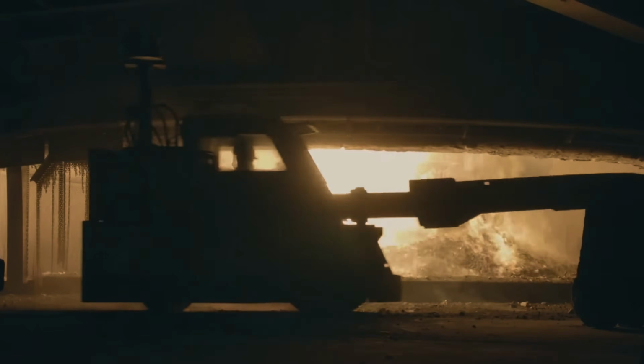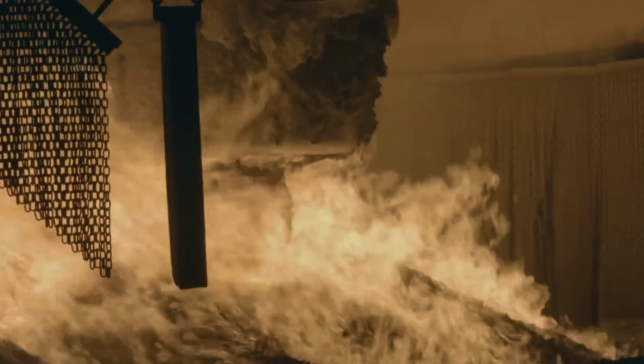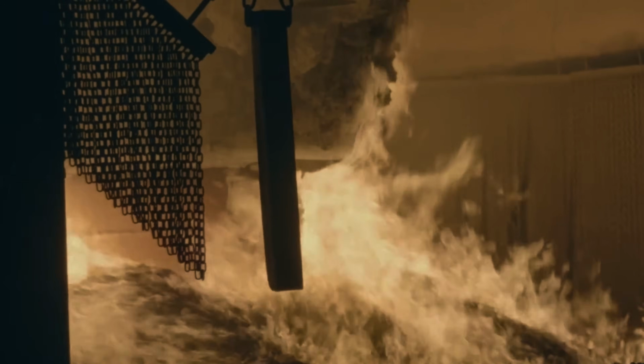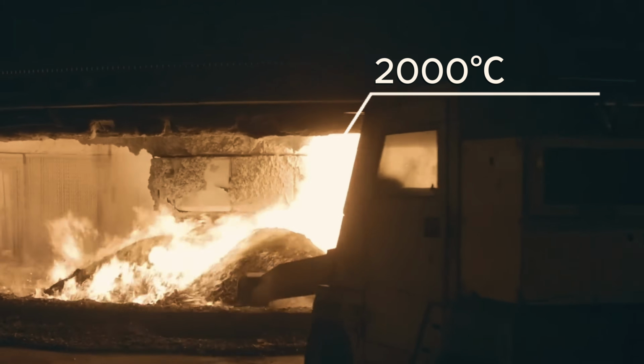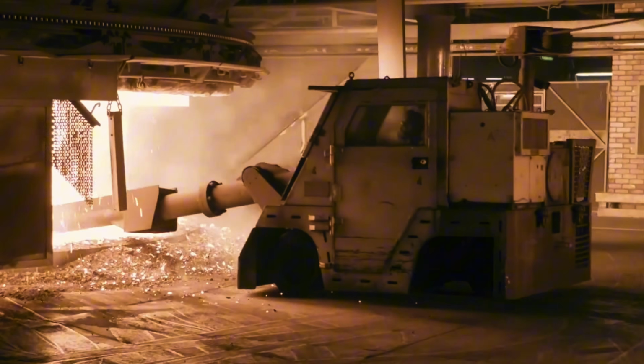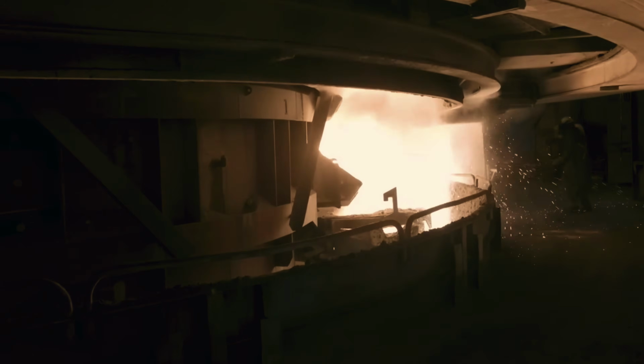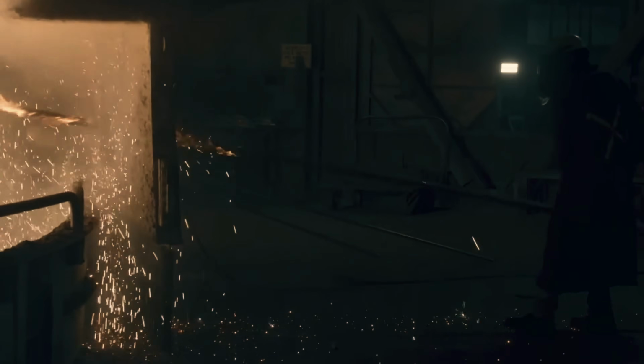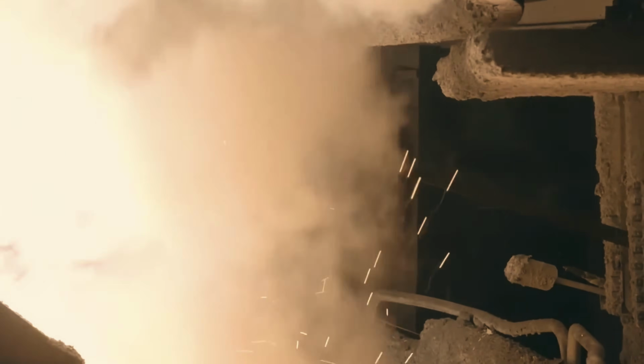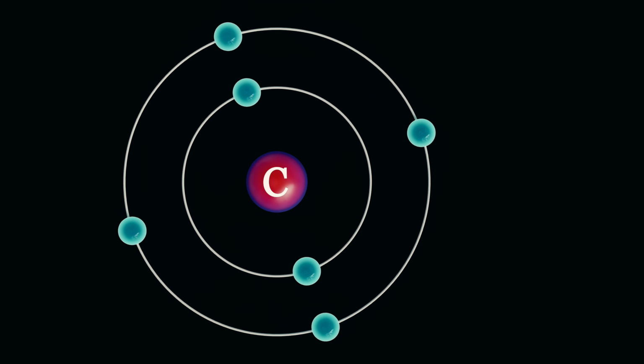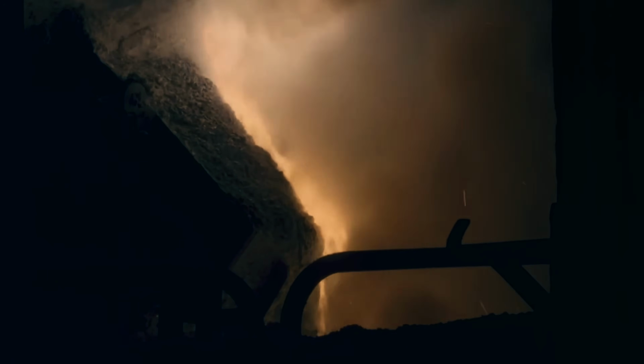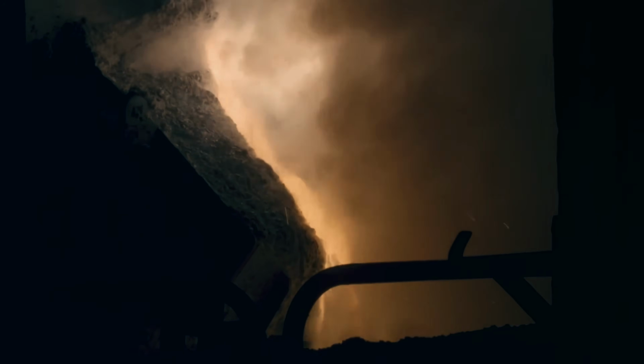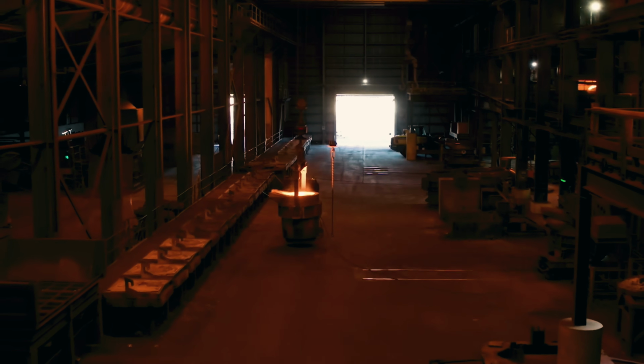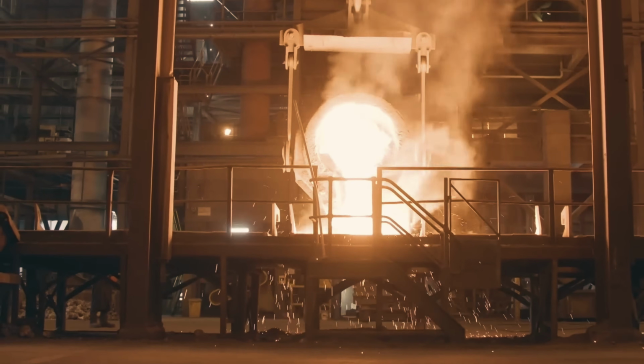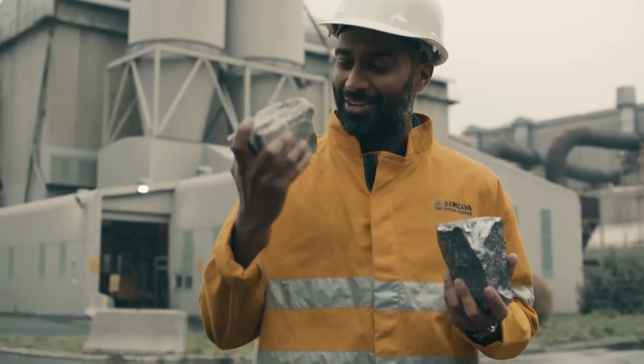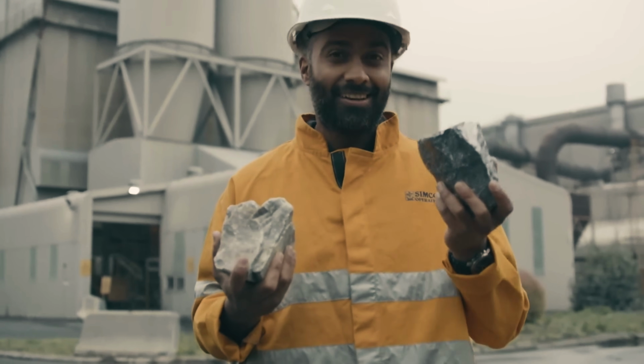That quartz gets dumped into an electric arc furnace alongside carbon, usually coal, coke, or wood chips, and heated to over 2,000 degrees Celsius, hot enough to melt steel twice over, hot enough that the electrodes glow like something out of a volcano. Inside, a chemical reaction strips the oxygen away from the silicon atom by atom, leaving behind molten metallurgical-grade silicon, roughly 98 to 99% pure. It's tapped off in a glowing stream, cooled and broken into chunks like dark, glassy gravel.